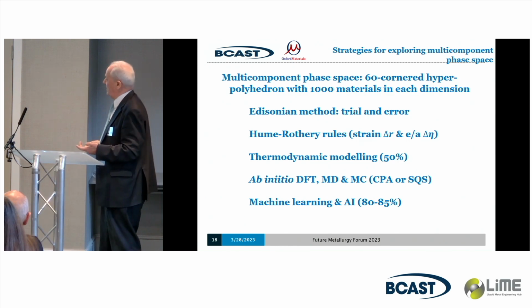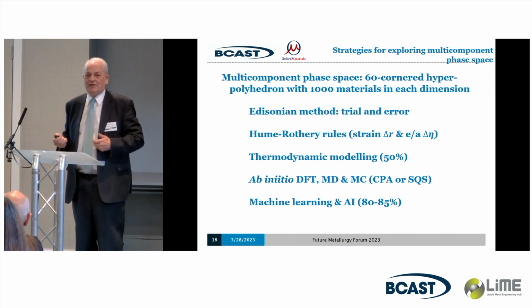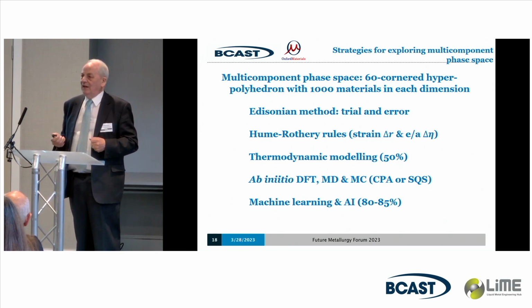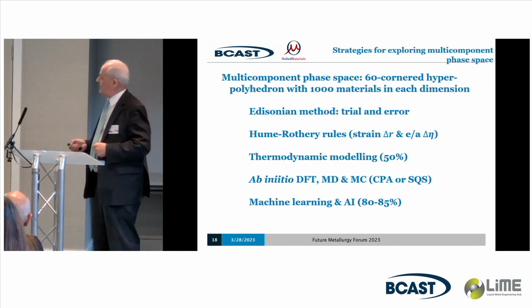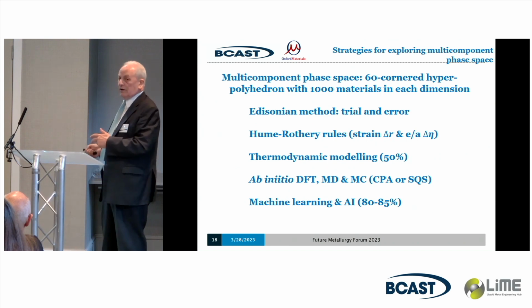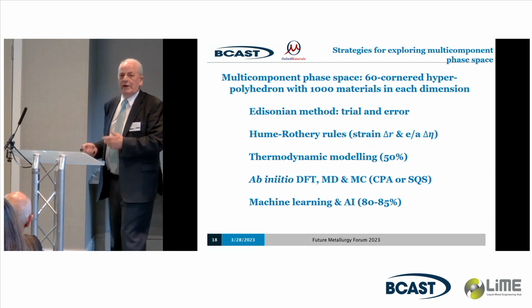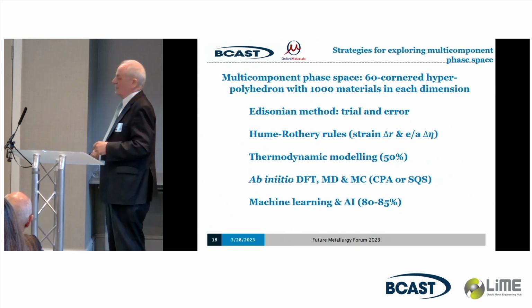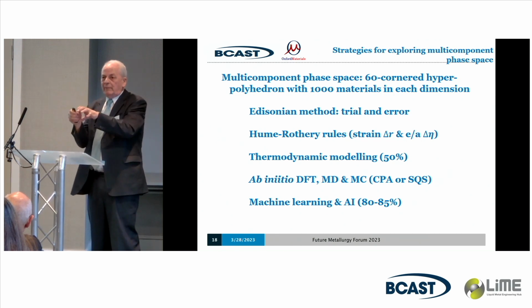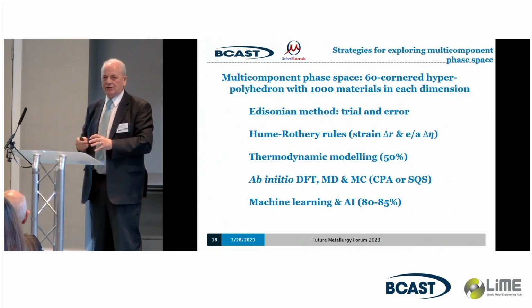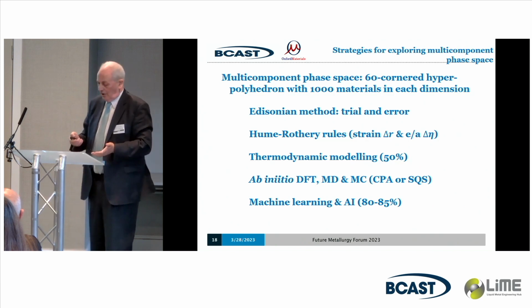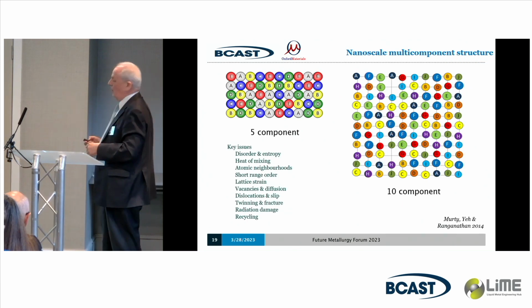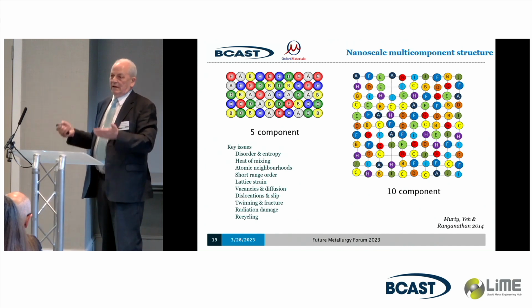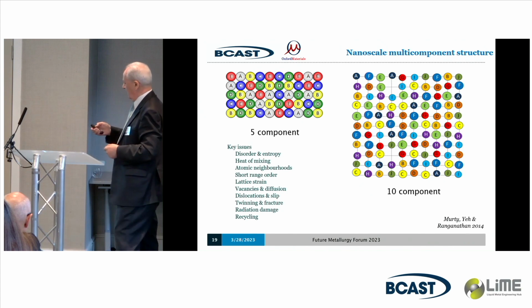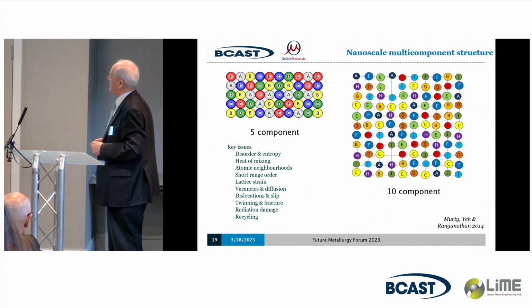So it turns out that it occasionally gives you the right answer, and it occasionally doesn't give you the right answer for these materials. And the machine learning guys came along and said, well, statistical inference, that's a great way of finding patterns and telling you what's going on without even needing to have any theories. Well, yes, that's good. If you've got a lot of data, and in this field, you get 90 to 95% accuracy on the training data. When you put it into the trial data, it tends to go down to 80 to 85%. But that's data points right in the middle of where you've already got loads of other data points. It's interpolation. If you want to extrapolate to somewhere else, forget it. You can't even do it. So the truth is that there's no alternative to experimentation. Supported by these, I don't want to overdo it. Those are useful methods.